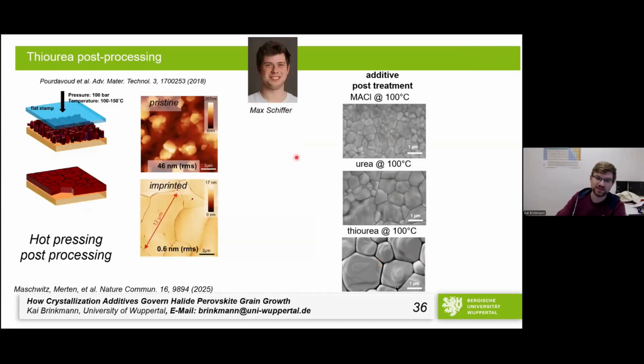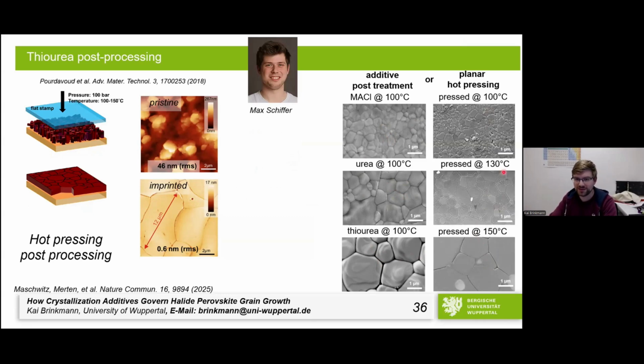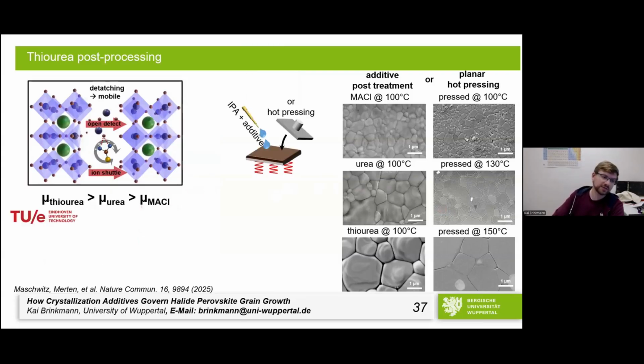A next technique that you can actually use this approach for, or this coarsening, is hot pressing. There you can basically use temperature just to increase the mobility. And to get roughly the same grain sizes for methyl ammonium chloride, we need to hot press at roughly 100 degrees. For getting the same as urea, we have to hot press at 130 degrees. And to get the same grain size as with thiourea, we had to hot press at 150 degrees. So another hint that it actually doesn't really matter how you increase the mobility across the grain boundary as long as you do. Yeah, exactly. This is against the order that we had around here. So thiourea, urea, and methyl ammonium chloride.